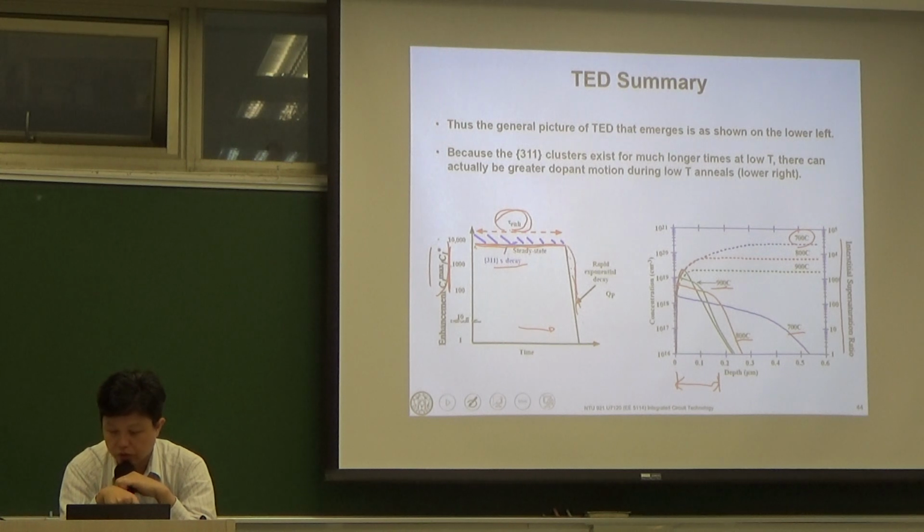It's quite different than what we talked about previously regarding the diffusion process. You see that at lower temperature you even have a larger diffusion profile. That's because of those defects.